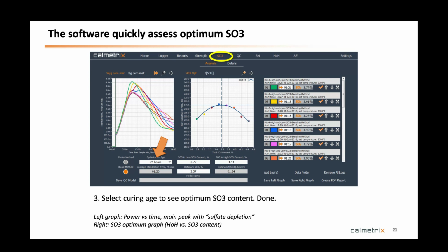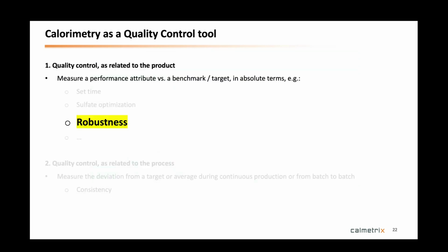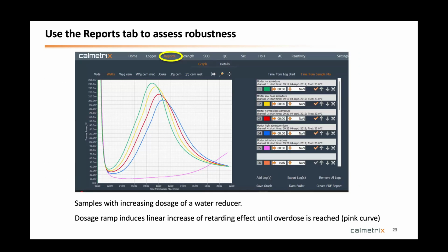And then robustness. Robustness is also something that's visually very easy to interpret. Here's an example of increasing the dosage of a water reducer in a concrete mix, and as you increase the dosage, every time you increase by a certain amount, you see that the curve shifts to the right, so the setting time gets higher and higher. And it's quite a linear response to the dosage.